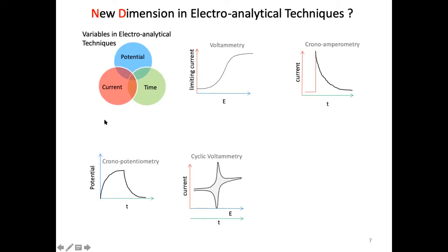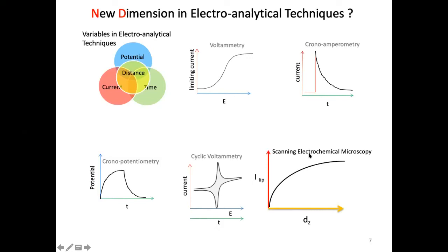Now, in all these four techniques, we have chosen the variables potential, current, and time. Suppose you add one more dimension, that is distance. Then we have one more technique called scanning electrochemical microscopy. What we do here is use a small probe called a tip or ultramicroelectrode, which we bring towards the substrate of interest or electrode, and measure the tip current as a function of distance between the tip, that is the probe, and the substrate. So this kind of response we get, and this response is very important because it has a lot of information about the kinetics of charge transfer reactions.